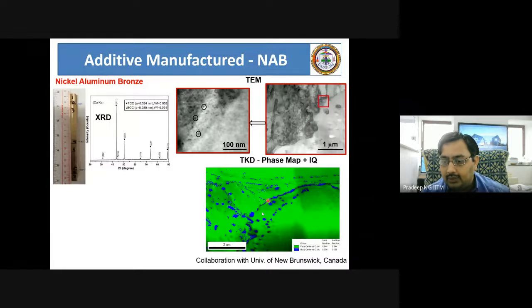Now this grain boundary region is what you see somewhere here, and all these nanoscale precipitates, you can now get the diffraction information, identify for their crystallographic structure. That means all the blue color precipitates are body-centered cubic, and the matrix material is a face-centered cubic structure.